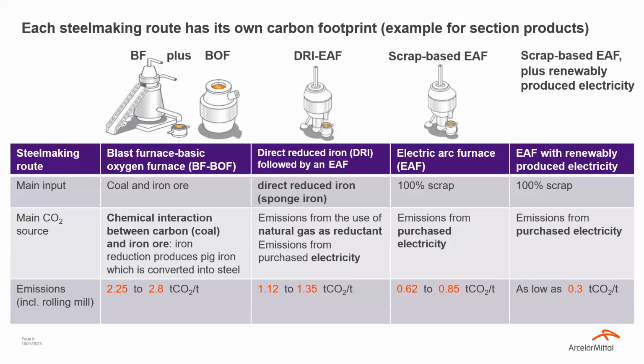And here once more, we have a little table that shows us the different production routes. Here we have an example for section and merchant bars products. If we start from the left, the blast furnace route uses coal and iron ore as main inputs. The coal plays the role of the reductant. As an order of magnitude in terms of carbon emissions, as a worldwide average, we can have in mind 2.5 tons of CO2 equivalent per ton of steel. Then we switch to DRI plus EAF, where we're still using iron ore, so still primary steelmaking, but instead of using coal, we're using natural gas as reductant. Here, in terms of order of magnitude, we roughly divide the number by 2, so we are at roughly 1.25 tons of CO2 equivalent per ton of steel.